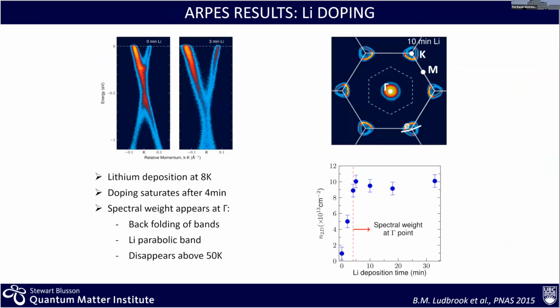So it's really two very different regimes. The biggest effect here, I think, in terms of induced superconductivity, following the work of Profeta, is really the different quantum confinement of wave functions and introducing lithium phonons into the problem. So it's really a different origin. Now what we're trying to do is go back to the very dilute and go up from there. Yes, and Christopher at UCLA is trying to do that with STM, to really combine the two pictures, real space and momentum space.